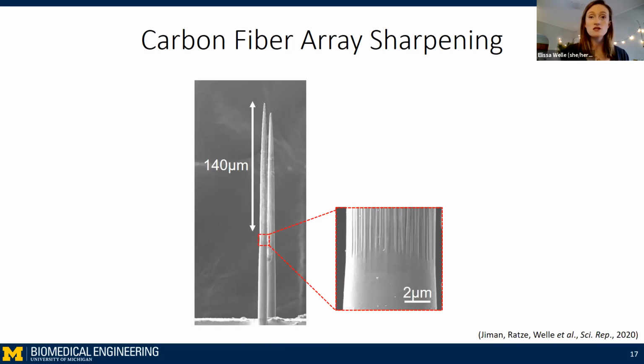And although the surface area is much larger than before, before we were looking at like 10 microns of exposed carbon in length, now we're looking at 140. You'll see that we still are able to record neural activity in peripheral structures.